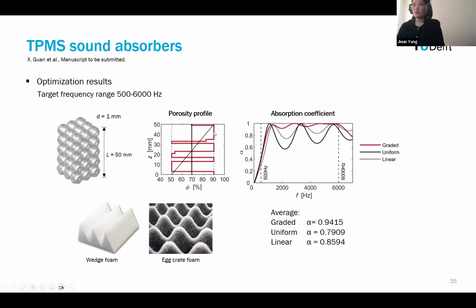But if we go back to this porosity profile, this is quite strange, because we usually think that to have broadband sound absorption, it is beneficial to have a structure with not changing that much. I mean, like a linear gradation, such as a wedge foam or some curved structure like an egg crate foam. But this was quite intriguing, so we decided to do further analysis on that.